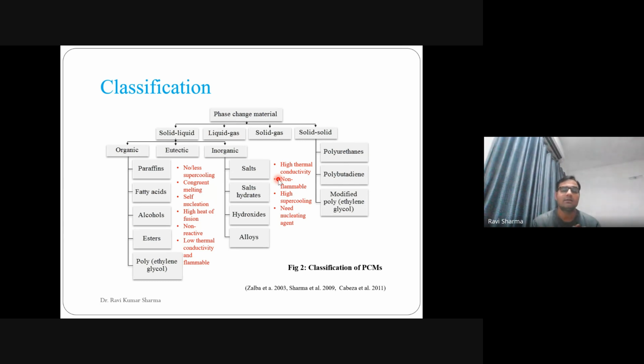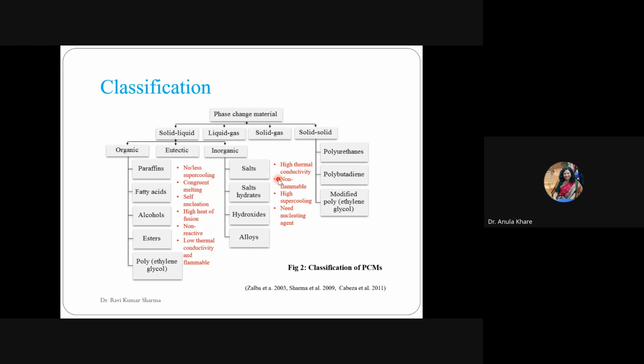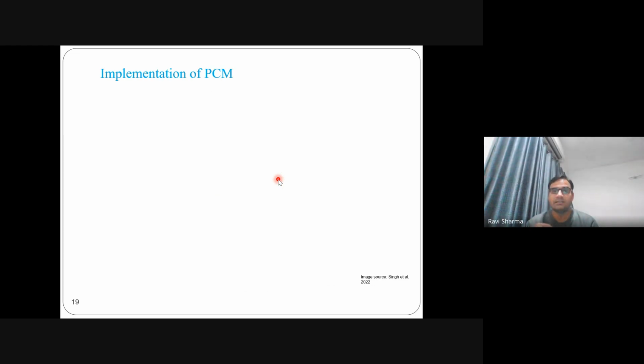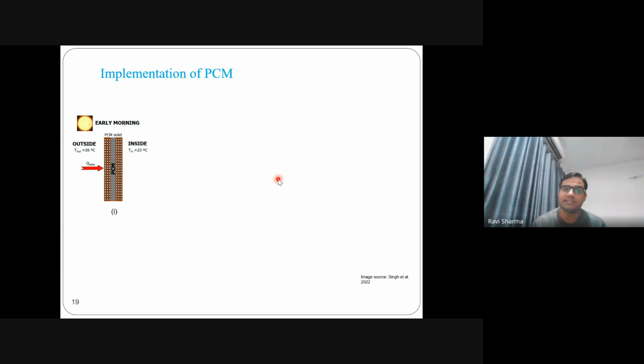These red color texts are the properties which these individual materials have. So the organic materials show congruent melting or effective solidification. They have high heat of fusion or latent heat, but they do have a very low thermal conductivity. For example, paraffin wax has a very good latent heat of the order of 150 joule per gram or 200 joule per gram, but the conductivity is of the order of 0.15 or 0.2 watt per meter Kelvin. So, since the conductivity is very low, there is a requirement to enhance their conductivity. Okay.